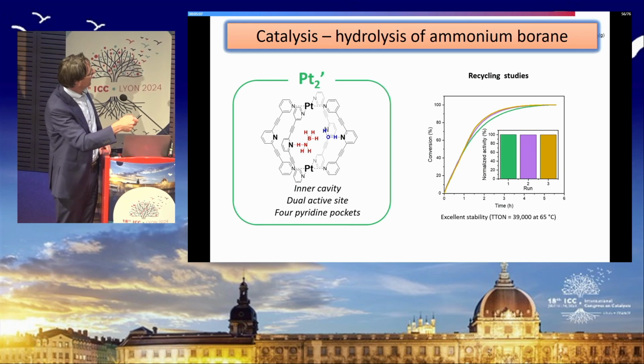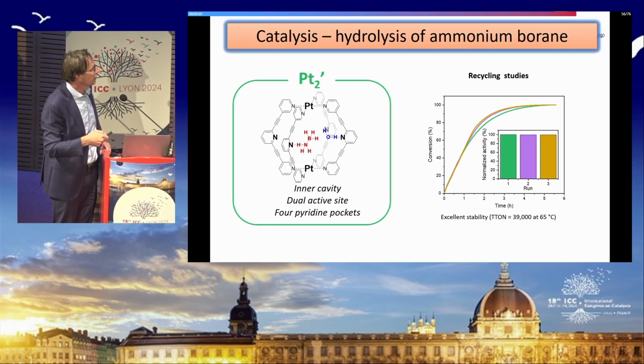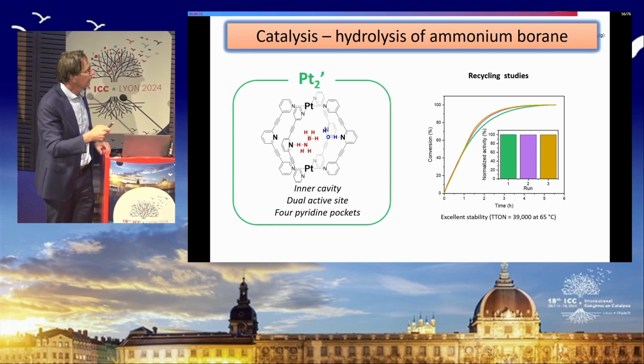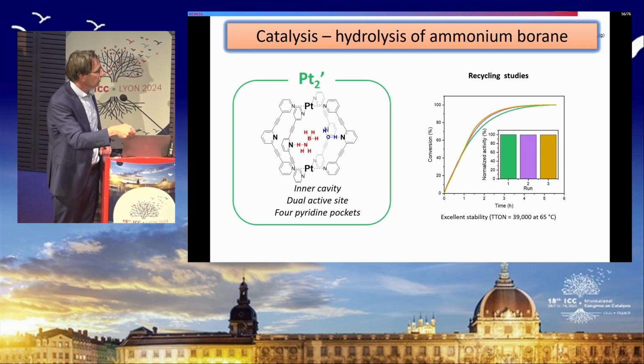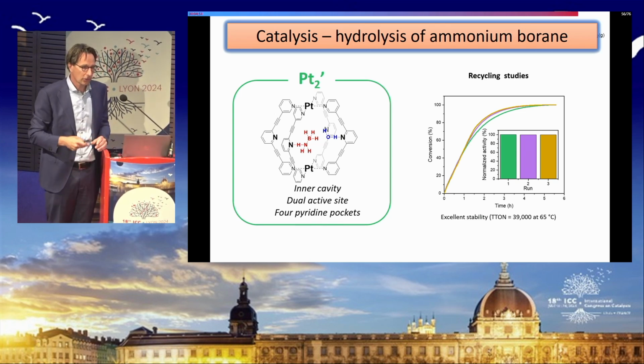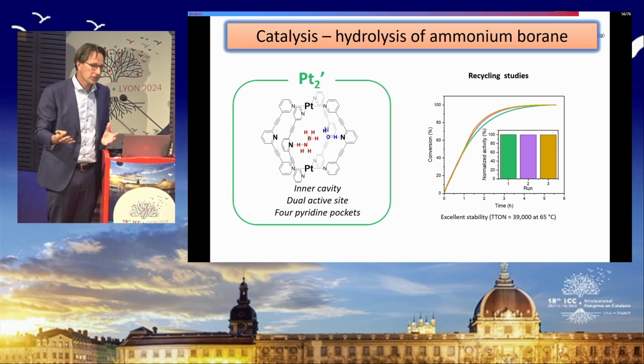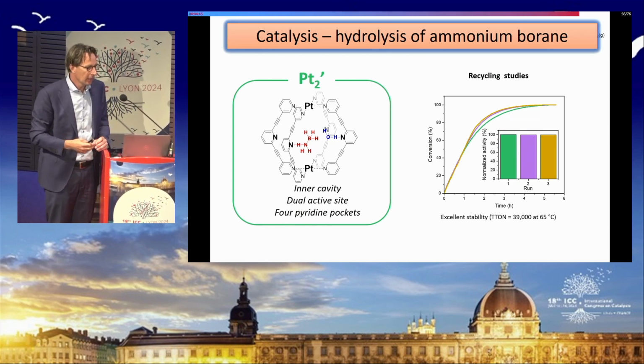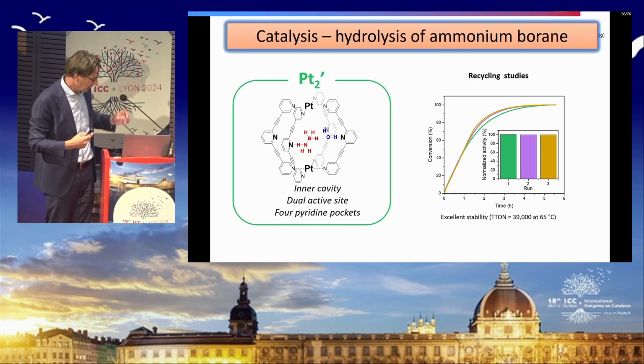Of course, now we have this heterogeneous catalyst, and we also look at recycling studies, and here you see overlays of 3 different runs, and you see that the rates are all the same for the 3 different runs, and they all go to completion, so total turnover numbers around 40,000. So it's a really stable system that can be used over and over again. Of course, this is just an initial study, but I can imagine that you can extend that to many other different cages and many other different reactions, if you like.